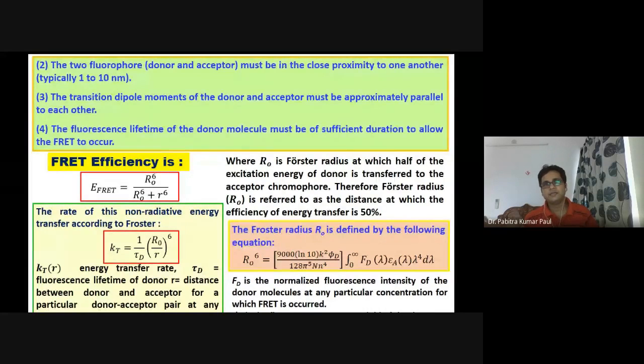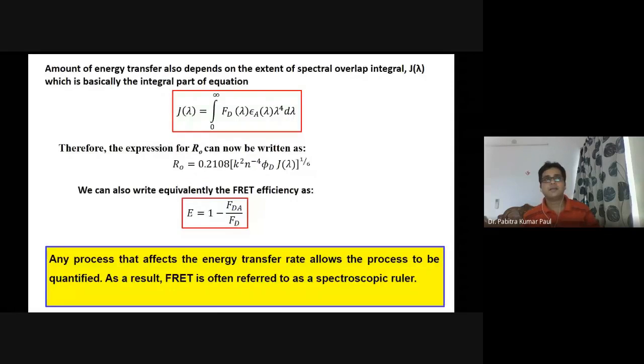And in this equation you see the FD, which is the normalized fluorescence intensity of the donor molecules at any particular concentration for which FRET occurred, and phi d is the quantum yield of the donor. The amount of energy transfer also depends on the extent of spectral overlap, which is basically the integral part of the equation. This J lambda is the spectral overlap, as I already mentioned in our previous slide, the green color shaded region. So this is basically the area under the overlap region of the curve.